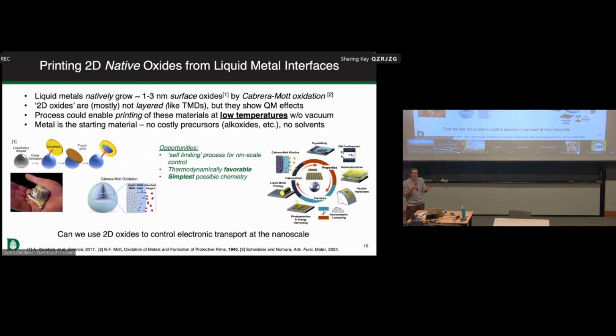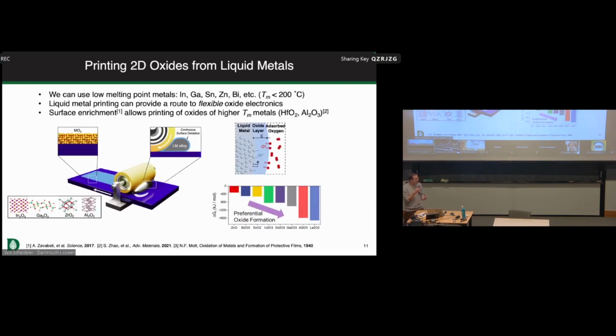So the fundamental problem that we're getting at in our group is how do we control the electrostatics of these materials at the nanoscale? So controlling the electrostatics means changing the doping of the material, changing the physical thickness of the layers, and being able to stack and influence the interfaces as well. So our version of this liquid metal synthesis uses a roller. We can deform that liquid metal droplet, and depending on the alloys that we design, you're also changing the composition of the surface oxide.